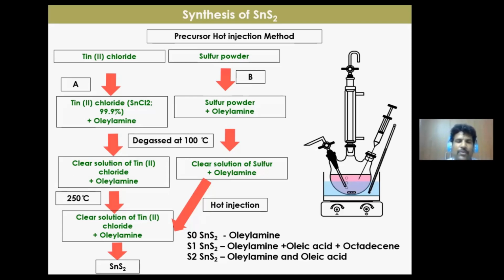And S1, SnS2, is synthesized using a combination of oleylamine, oleic acid, and octadecene. We have chosen a smaller amount of oleylamine and oleic acid in a large amount of octadecene to check the output. The third one we have chosen is S2, SnS2. In this, only oleylamine and oleic acid are used to check the morphology change. So octadecene in this sample is avoided. Hereafter I will mention S0 for oleylamine, S1 for oleylamine, oleic acid, and octadecene, and S2 for oleylamine and oleic acid. After synthesizing this material, the materials were washed with acetone and then dispersed in hexane, cyclohexane.